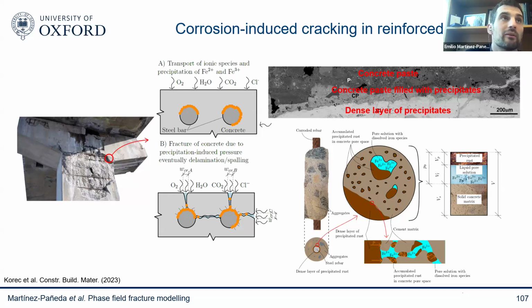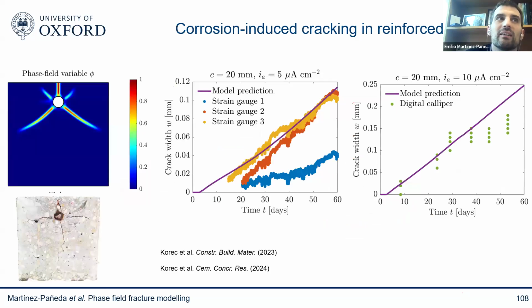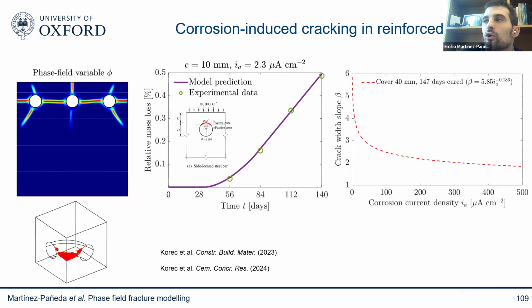So concrete structures have been reinforced with metallic rebars, of course. And when you do that, the beauty of it is that it allows you to not only predict the cracking patterns that you see here, but also the cracking patterns that you see in experiments. And by the way, I should emphasize we use Wu's model here, so the phase field cohesive zone model. But also, it allows you to critically go from laboratory experiments to large-scale phenomena. And this is not only a matter of space scales, but of time scales.